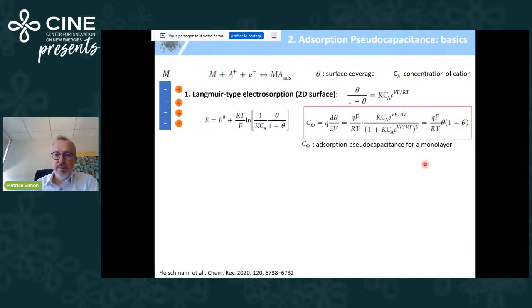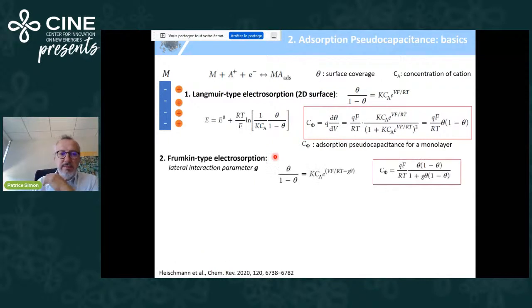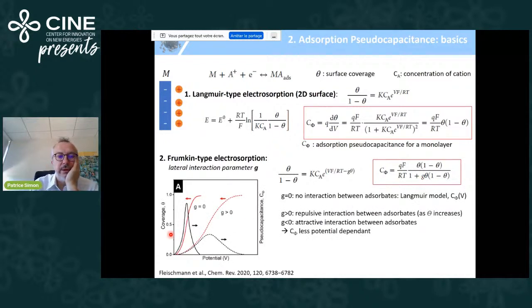Now, from this very basic Langmuir model, you can extend the model by considering a lateral interaction parameter G, moving to the so-called Frumkin-type electrosorption process. And this G parameter is going to modify your capacitance and theta coverage. So this is the change of the surface coverage theta versus the potential. And this in black is the change of the pseudocapacitance, taking into account the G parameter.